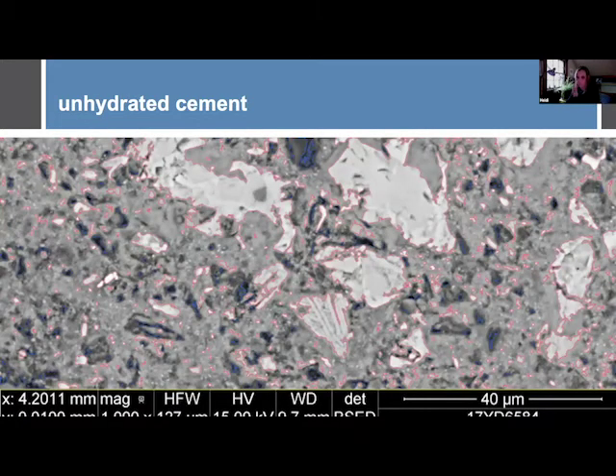So zooming into this is a very dense CMU. We can see the void structure that we looked at on that previous image of the microscopic block. And in blue, we see the void structures that we saw in the last image. But something that we see here is that in red is all of this unhydrated cement. Now, this is kind of like the way that we traditionally make block. We end up with a lot of this unhydrated cement. So it's pretty much wasted cement in there.